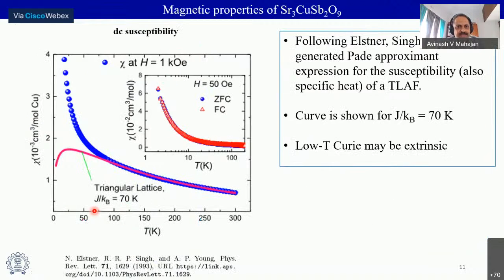Okay, then since we suggested that it could be a triangular geometry, there is an old paper by Elstner, Singh and Young where they model the triangular lattice antiferromagnet, and based on Padé approximants, they give an expression that you might expect for the specific heat as well as the susceptibility as a function of temperature for a triangular lattice antiferromagnet with only nearest neighbor interaction. So based on this input, we draw here the solid curve, which is for a triangular lattice with a nearest neighbor interaction of 70 K.